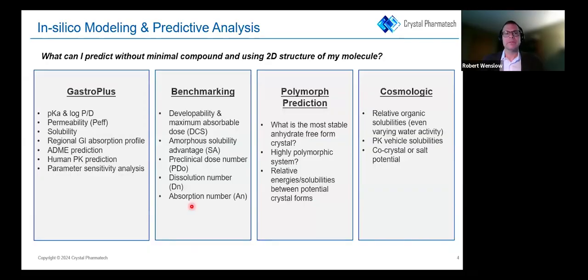So what can you predict with very small amounts of material and a two-dimensional structure? Specifically with GastroPlus, you can predict pKa, log P, permeability, and solubility. Now, on the solubility point, no one's doing a great job of predicting solubility. That's one of the big concerns. But with just very small amounts of material, less than 25 milligrams, we can find a crystal form, not necessarily the best crystal form, but get a crystal form solubility, and also an amorphous solubility with some of the techniques that I'll be showing, and get an understanding of the advantages of using an amorphous form over a crystalline form.